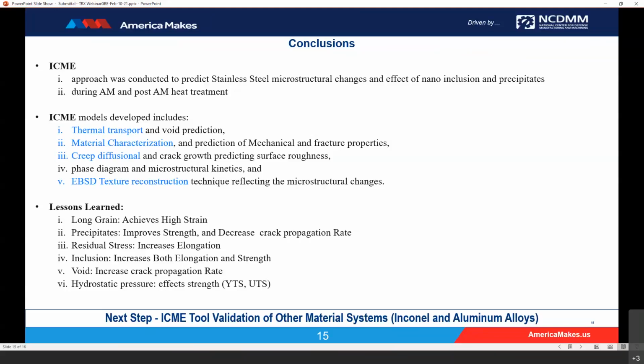Lessons we learned in this process are that long grains translate to high strain, precipitates can improve strength and decrease crack propagation, residual stress increases elongation, inclusion increases both elongation and strength, voids can increase crack propagation, and hydrostatic pressure affects strength. I think a further conclusion of this is that sometimes items that you think would have a negative effect, if properly organized with other considerations, can have a positive effect. That's why bringing the ICME tool to understand the overall process and optimizing that can help you find the best solution among a large variety of options.